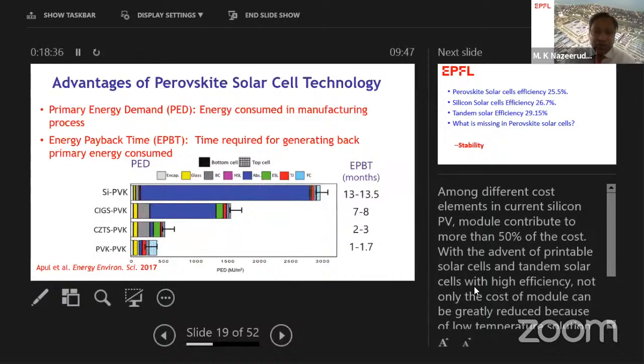We are comparing here the silicon perovskite tandem configuration, CIGS perovskite tandem configuration, followed by the thin film and perovskite tandem configuration, perovskite tandem configuration. The primary energy consumed, and the energy to be generated by the solar cells, requires only 1 month for the perovskite solar cells. For comparison, silicon solar cells may require over 1 year. So that shows the primary energy consumption of these solar cells.